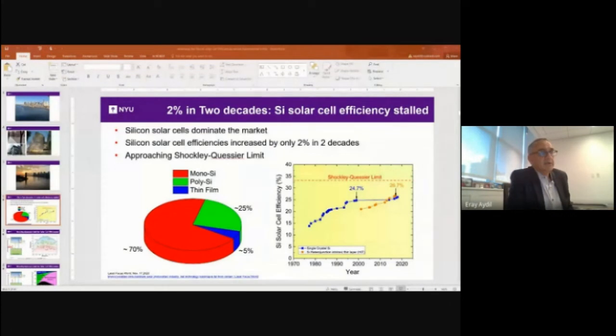If, on the other hand, you have light that has energy larger than the band gap, you create excited electrons and holes deep up in the conduction band or in the valence band. Now, those excited electrons quickly relax to the band edges by colliding with the lattice atoms and by making them vibrate, in other words, creating heat. And that energy is lost as heat. You don't get it as potential voltage or as current. So that's energy lost as heat. So if the band gap is too small, then you lose a lot of energy by heat.